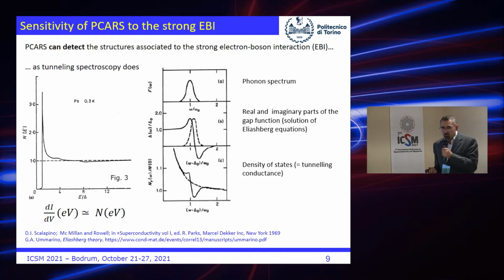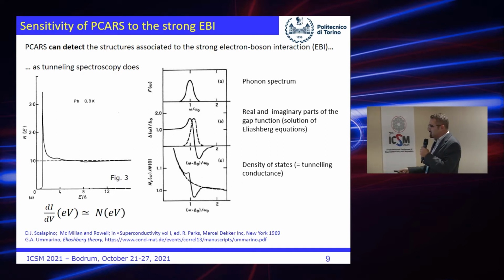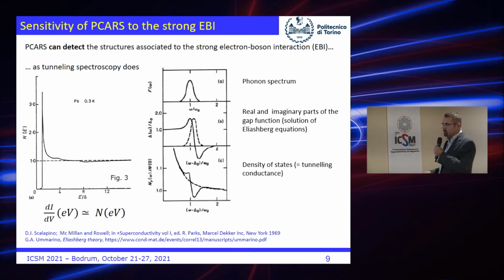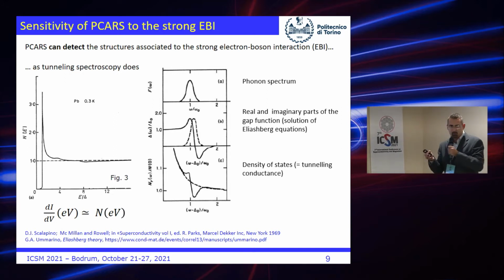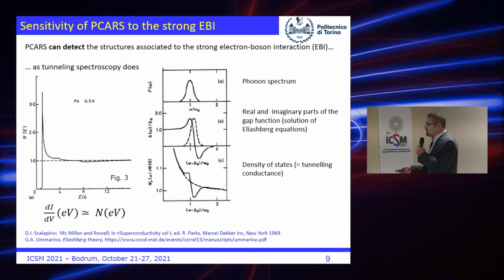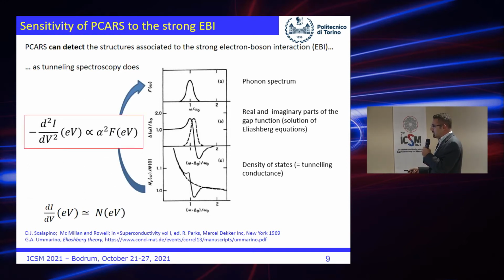But what we do is the inverse. So we start from the experiment, and we want to extract information about the phonon spectrum, the boson spectrum more in general. The way is very simple, because if you take this curve and you calculate the derivative, and you change the sign, you obtain exactly that. So the idea is that you start from the spectrum you measure in tunneling, you calculate the derivative, that means the second derivative of the current with respect to the voltage, and you obtain the information of the phonon spectrum.